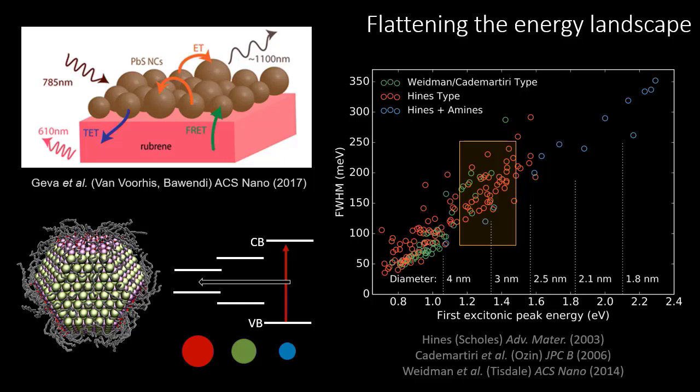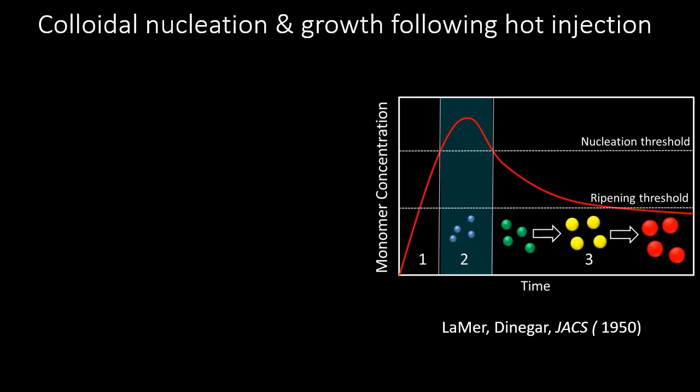I show here a summary plot compiling all literature results, organizing reported lead sulfide quantum dots by their size or optical gap and their ensemble linewidth. Because these are quantum-confined materials, if they are size-dispersed, that contributes to the emission linewidth through heterogeneous broadening. What we found was that dots with physical sizes around 3 nm, or first excitonic peak energies around 1.3 eV (just beyond 900 nm) — the kind we were looking for for upconversion — had very large full-width half-maxima of 6, 8, or 10 kT, larger than the well-optimized slightly larger dots that seemed to work better.